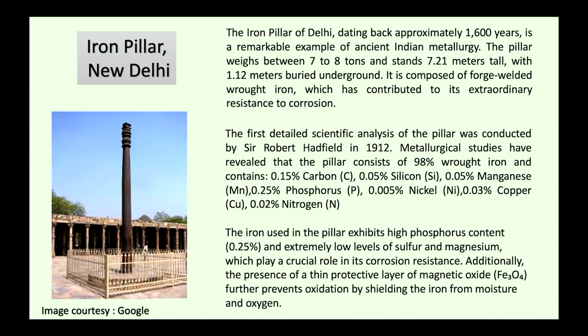1912. Metallurgical studies have revealed that the pillar consists of 98% wrought iron and contains 0.15% carbon, 0.05% silicon, 0.05% manganese, 0.25% phosphorus, 0.005% nickel, 0.03% copper, and 0.02% nitrogen. The iron used in the pillar exhibits high phosphorus content